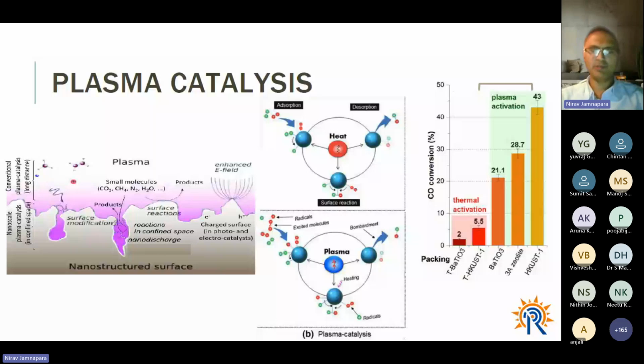Now, what does plasma catalysis actually do? What plasma does is it brings down the activation energies for reactions, and therefore makes the reaction possible to be executed at much lower energies, and therefore lower temperatures. And further, the catalysts bring these activation energies further down. Carbon dioxide, CO2, is a difficult molecule to crack, and therefore plasma alone or catalyst alone cannot bring the energy down to such a level that CO2 splitting becomes an economic process. But plasma and catalyst combined have proved to be a very attractive option.